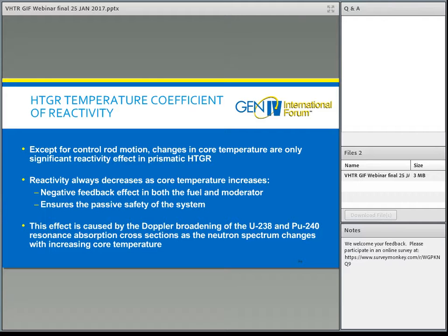Looking at the second way of protecting the particles, which is controlling the heat generation. The control of the heat generation in this reactor, like in many other reactors, relies on a negative temperature coefficient of reactivity. Putting that into the simplest terms, the definition is that as the temperature increases, the reactor power level decreases. This is a built-in physics effect in this type of reactor. As shown there, the reactivity, which is the tendency of the reactor to increase in power, decreases as the core temperature increases. That provides a negative feedback effect both in the fuel and in the moderator to shut down the reactor, or tend to shut down the reactor, as temperature increases inside the reactor.